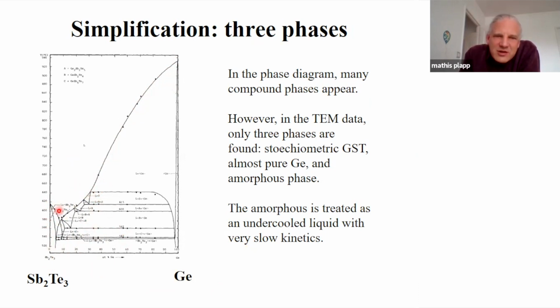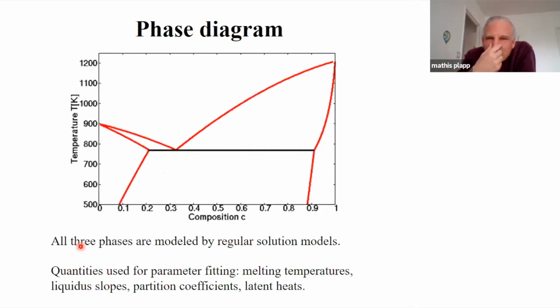You also can see that there are a lot of different stoichiometric phases. Actually, in the TEM data from our partners at ST Microelectronics, they say that they only can see the stoichiometric GST phase. So we have limited ourselves to three phases, namely germanium, stoichiometric GST, and the amorphous phase. So here's the phase diagram that we have obtained. It's of the eutectic type. We have fitted this to various data available from the literature, the liquidus slopes, the melting temperatures, latent heat, and so on. This is really quite in the spirit of CALPHAD.